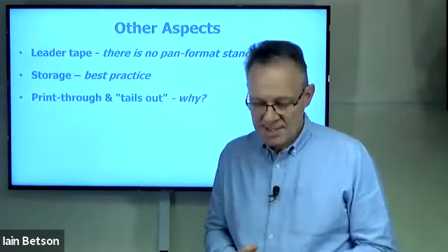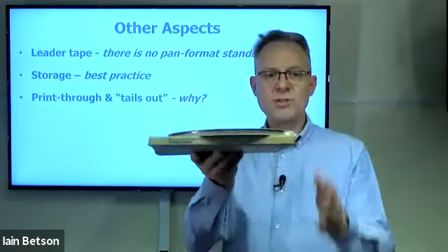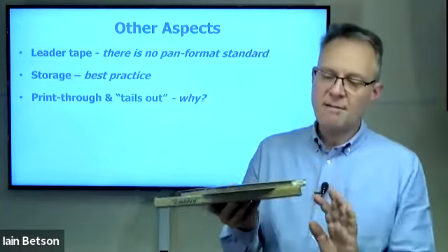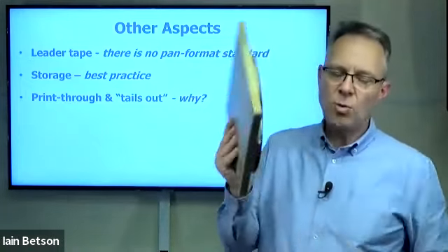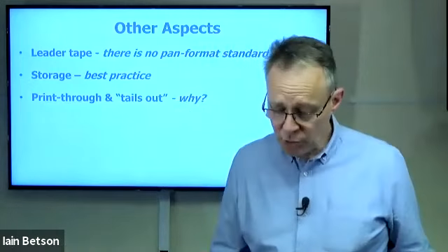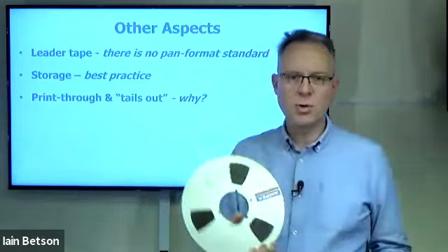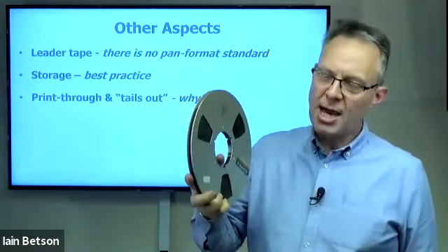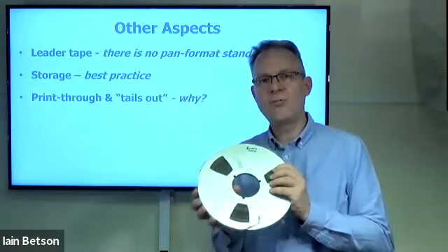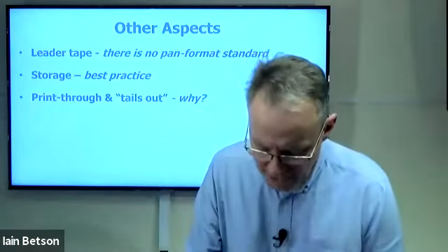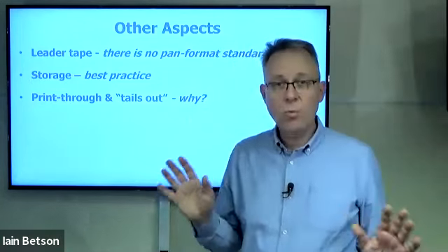Storage best practice. Well, as I said earlier, I was stacking all these tapes up one on top of the other, which is not the best idea. They do get, therefore, edge crushing. The best idea is pretty much store them upright. Unfortunately, this is the problem with so many old tapes and archive tapes. They've not been stored in the best conditions. Not put in your shed, not put in the loft. Try and keep them where you live, so it's reasonably warm and not too humid, not too hot, not too cold.